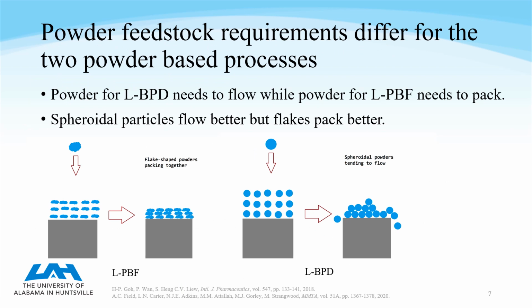So these two different methods have different requirements because they're relying on different mechanisms. So what we think is that flake-shaped powders will be better for powder bed fusion because they're going to pack better and stay in place in that powder bed, whereas spheroidal powders are going to be better for blown powder because they flow better.